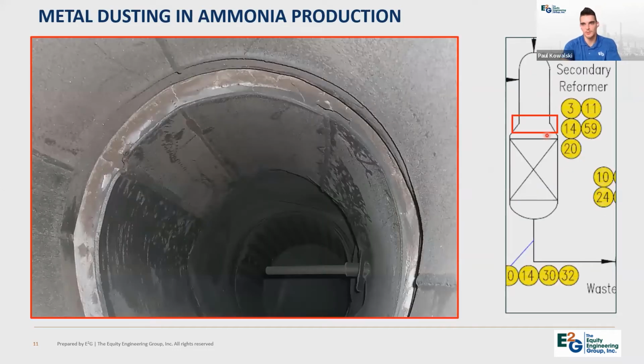So several pictures, again. In this picture, we're looking upwards from this transition section. So we can see the process gas inlet nozzle here, and then up here would be where the air is being injected and combustion is occurring in this region. And we can see the burner liner, which again is an Inconel material. It's intact here as well as in the transition, but here we have exposed refractory, and you can see that the burner liner at this transition location was basically completely wasted or turned to dust, hence metal dusting.